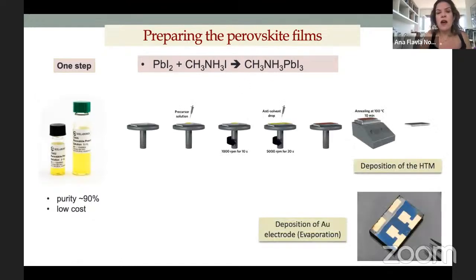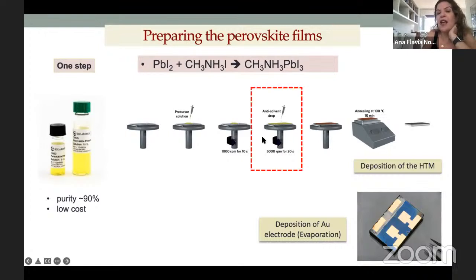So then when you have the precursor with all the components, you go to your spin coater and you start depositing the precursor solution. You can, for instance, purchase the precursor solution from Solaronix, or you can prepare it in the lab. It's very, very easy. So you go to a spin coater, and just a few seconds before you switch off your spin coater, you drop what we call an antisolvent. This is the most important step. I have a video to show you here that in that moment, we see the formation of the perovskite.